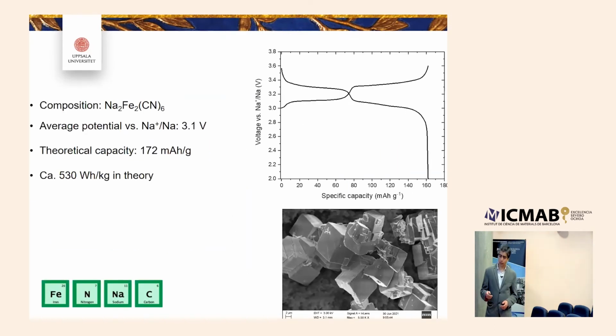So as I said, it has two flat plateaus - that's the interesting part with this material, relatively high capacity. The average potential is almost 3.1 volts. You can make big particles and cubes of this material, which is an advantage. Ion diffusion is relatively fast, and it's all based on naturally abundant elements.